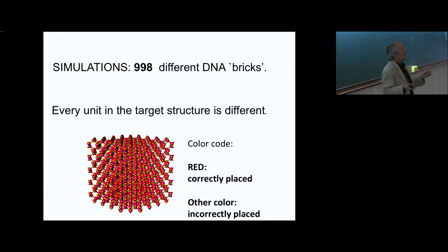And so if you have that, the particle can bind to four neighbors. You can see some green and blue things, those are the complementary patches, and we give them the properties of real DNA. That is, you take random DNA sequences, and then we get from the online databases, DINAMelt, something that implements the SantaLucia rules online, we compute what the binding free energy should be. This model therefore contains the experimental binding free energies for all the patches. And then we just see what happens if you take this system and look at the self-assembly.